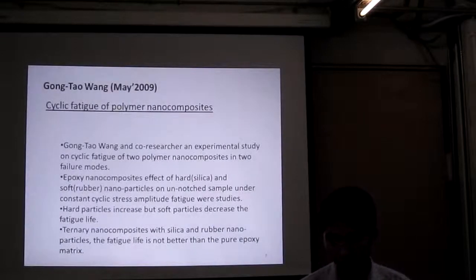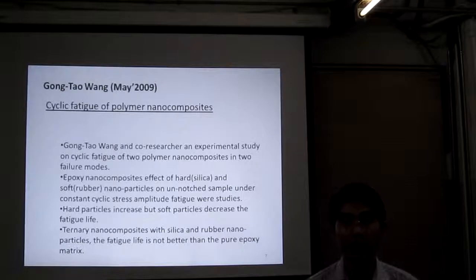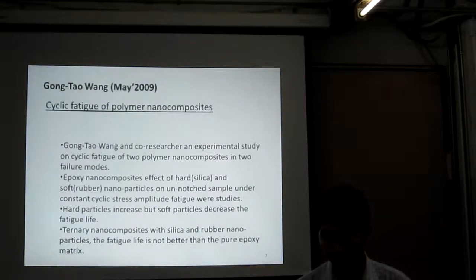And next, cyclic fatigue of polymer nanocomposite. This research studied cyclic fatigue of two polymer nanocomposites in two failure modes, where the effect of hard epoxy nanocomposite and soft nanoparticle on an un-notched sample under constant cyclic stress amplitude fatigue was studied. In this research, it was found that the hard particle helps increase fatigue life, but soft particle decreases the fatigue life. And the hybrid nanocomposite with silica and rubber nanoparticle, the fatigue life is not better than the pure epoxy matrix.